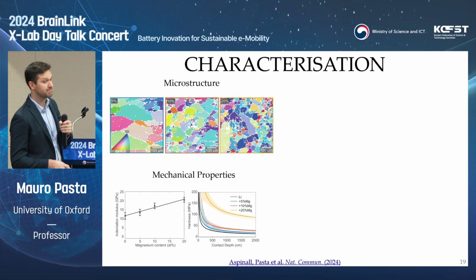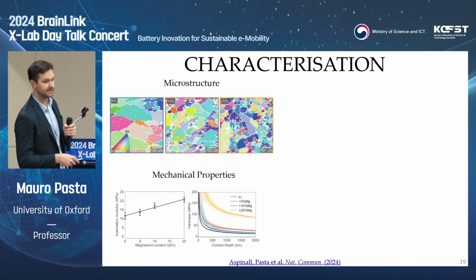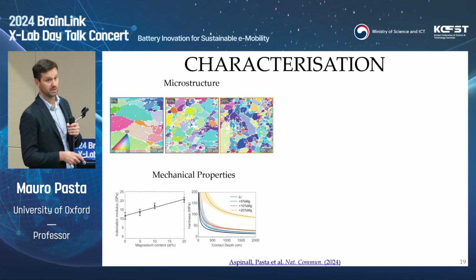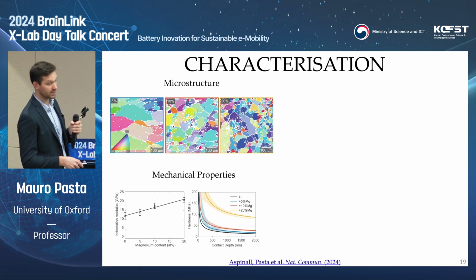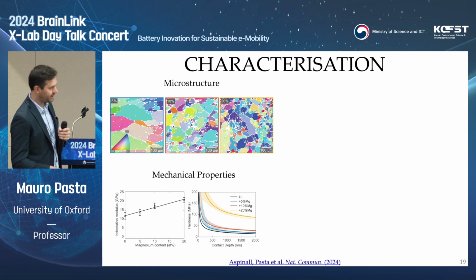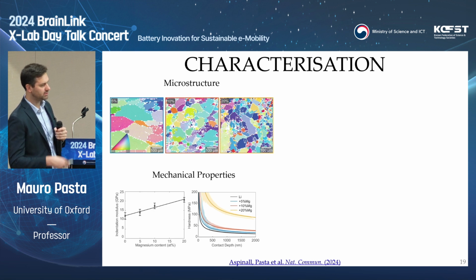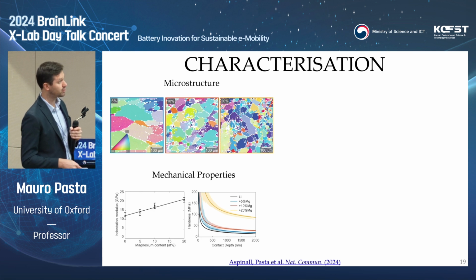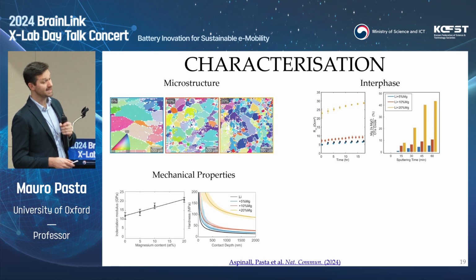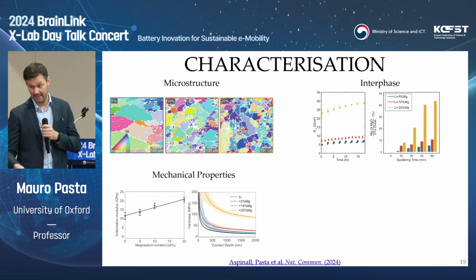So one indent is maybe in the order of, let's say, 1 to 10 microns. You can perform several indents within a single crystallographic orientation and get the crystallographic orientation dependence of these mechanical properties. You can get hardness, for example, as a function of magnesium. You can get elastic properties, plastic properties as well. You can characterize the interface formed between your alloy and the solid electrolyte.